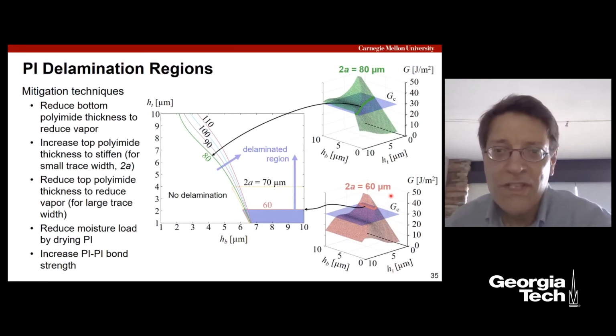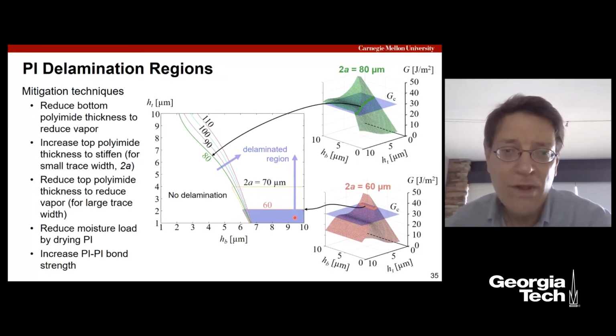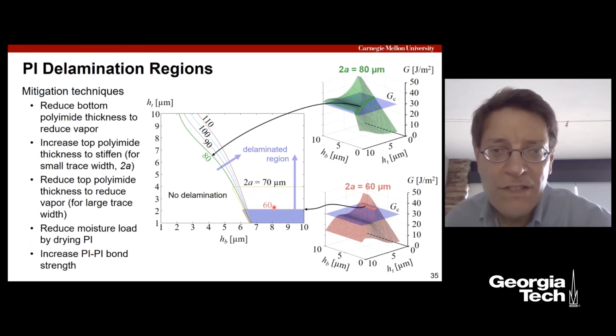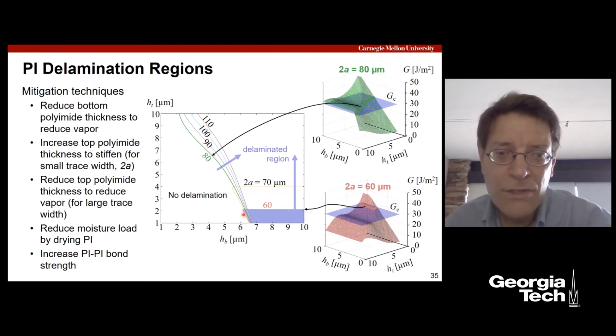Are we making the trace 60 microns wide, 80 microns wide, or whatever? And what we find is that as we make the trace wider, it changes the delamination region. In the case of the 60 micron trace, we're going to delaminate, according to the model, in this purple region where we have a large bottom polyimide and actually a modest top polyimide.